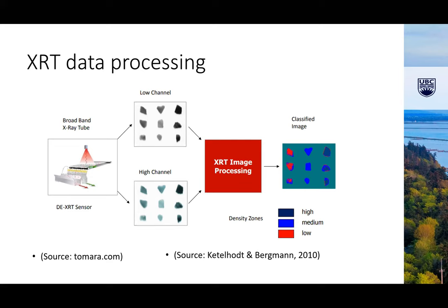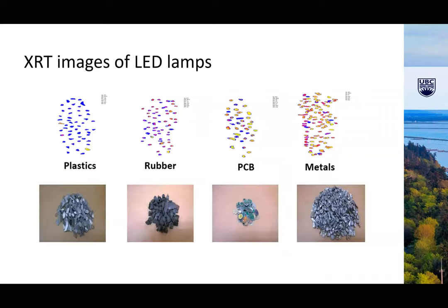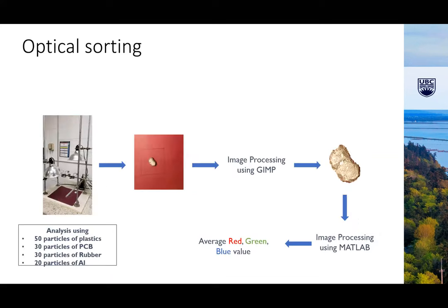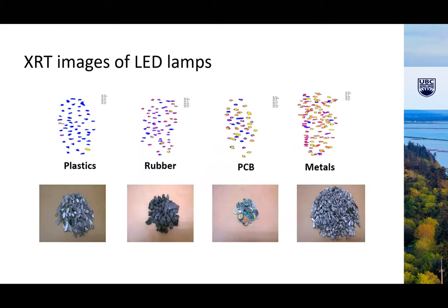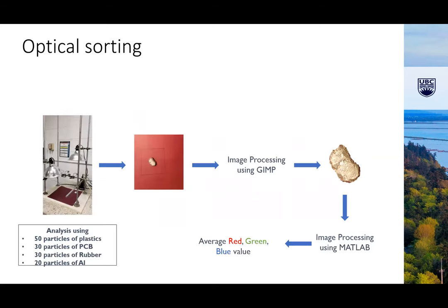And then the image is processed. Then we can classify the particles according to the density zones. So that way we can separate by density. And we did that. So we found that we did a really good job, because the plastic, rubber, and PCB and metals were quite well separated, sorted by the XRT. So this is on LED lamps.